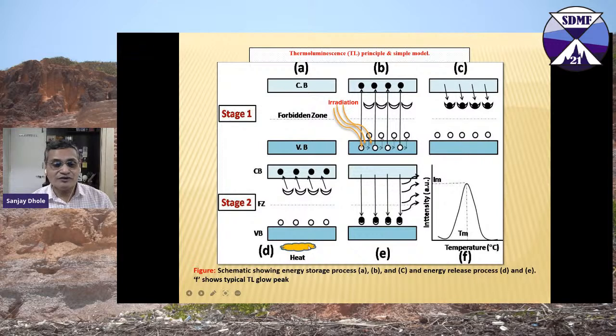Now when you heat it, all those trapped electrons get sufficient energy. The thermal energy is 0.025 electron volt, and if you heat it more than 300 degrees Kelvin, that is 400-500 degrees Kelvin, then definitely the energy is more than 0.025 electron volt. So all the deep levels, the electrons will detrap going into the conduction band, stay for a certain amount of time and de-excite. By de-excitation, it gives a light. This gives a photon.